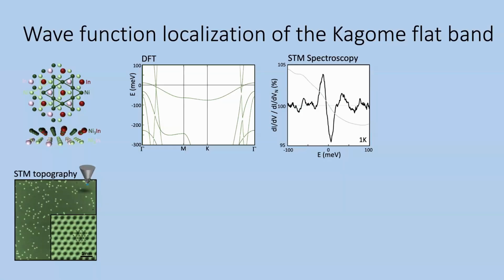So we apply this method to nickel-3 indium. First of all, the DFT calculation predicts that the wave function is mainly contributed by DXZ orbitals. However, as you can see, the DXZ orbitals don't capture only the flat band, they also contribute to the light bands, Dirac-like bands that disperse around the flat band. So this is not really the local moment that produces the flat band, but the flat band is mainly constructed by these DXZ orbitals, and they are localized within these triangles, corner triangles of the kagome crystal. So this is where DFT predicts that the flat band should be localized.